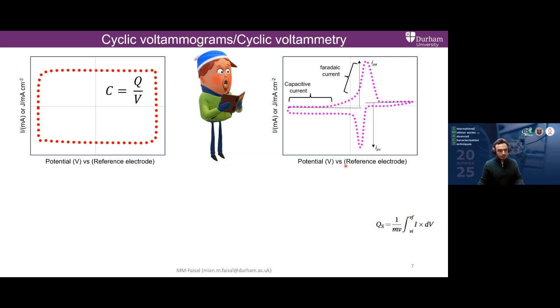In terms of battery-grade material, you will have very distinct oxidation and reduction peaks in the cyclic voltammogram. In some materials, not very often in every material, you do have some EDLC contribution, and that tells you that there is still an electrostatic accumulation, but there is a broad Faradaic reaction happening at the electrode interface and in the bulk of the material, and that's why it gives you the oxidation and reduction peaks in the cyclic voltammogram.